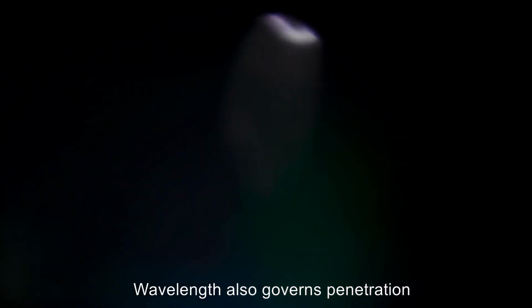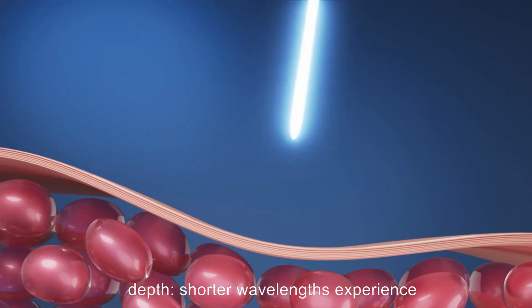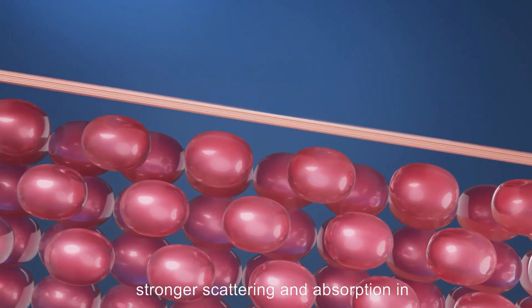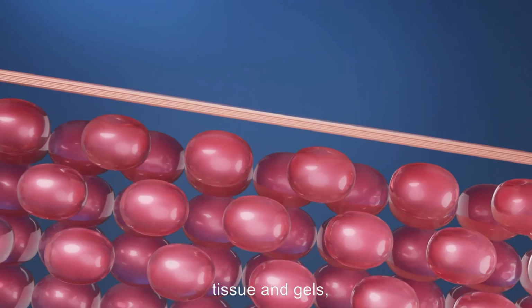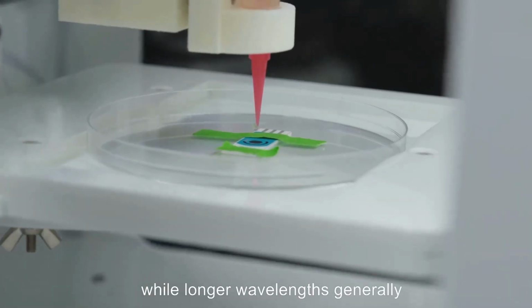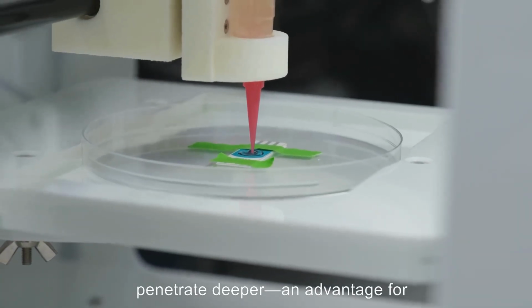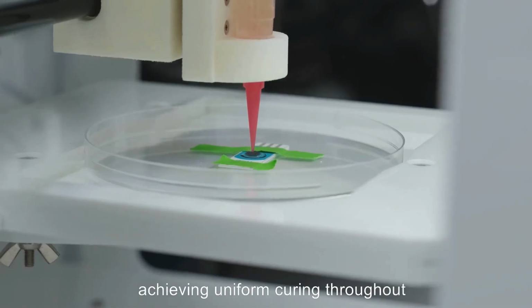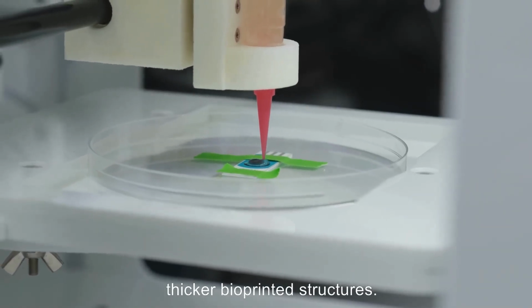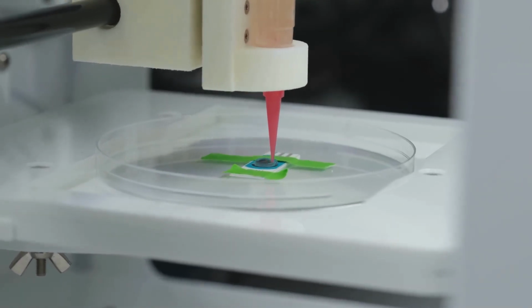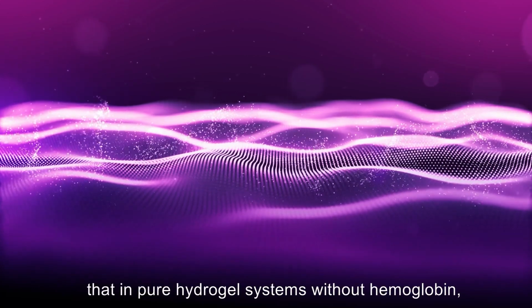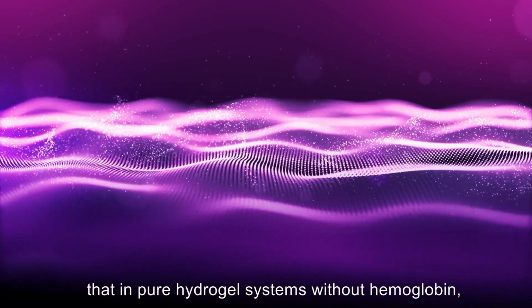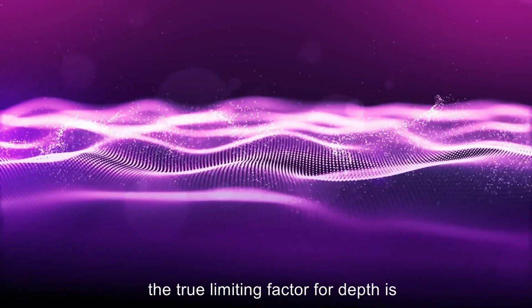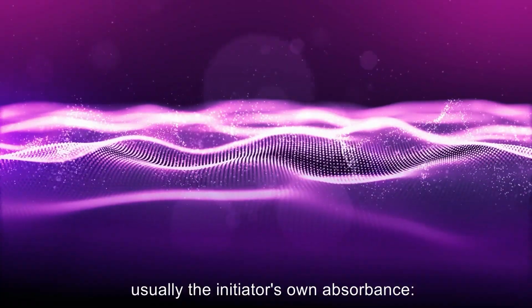Wavelength also governs penetration depth. Shorter wavelengths experience stronger scattering and absorption in tissue and gels, limiting depth, while longer wavelengths generally penetrate deeper, an advantage for achieving uniform curing throughout thicker bioprinted structures. It should be noted, however, that in pure hydrogel systems without hemoglobin, the true limiting factor for depth is usually the initiator's own absorbance.